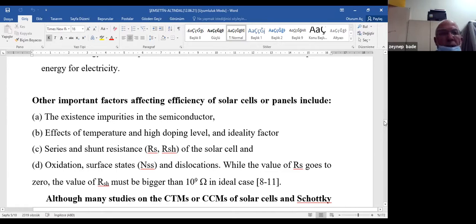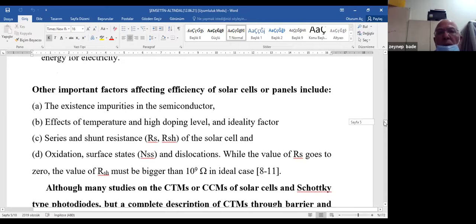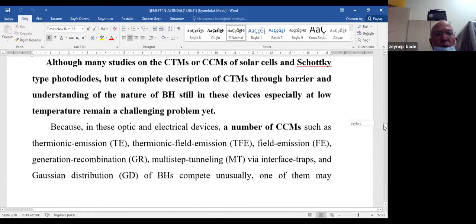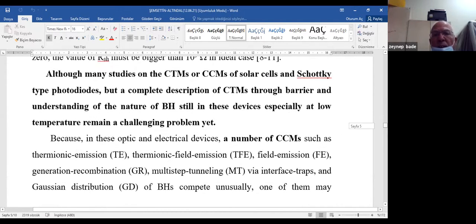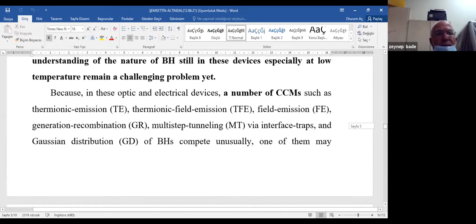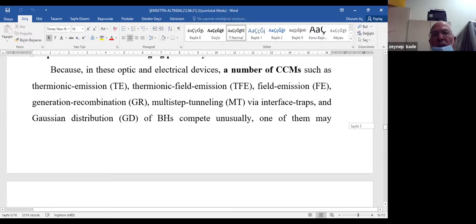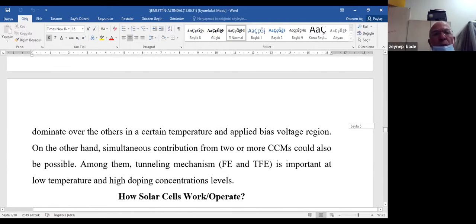Yes. Some other important factors that reduce the energy loss are the excess of impurity in the semiconductor, the effect of temperature, the doping level, the ideality factor, series and shunt resistance, and oxidation or surface states. The conduction mechanisms of these solar cells depend on processes such as thermionic emission, thermionic field emission, generation recombination, multi-step tunneling via interface traps or surface states, and Gaussian distribution of barrier height. They compete, and usually one of them may be dominant over the others in a certain temperature and applied bias voltage range.